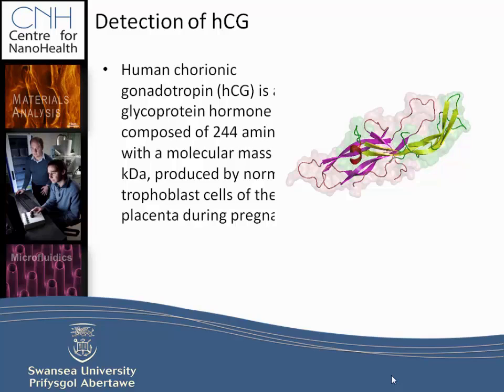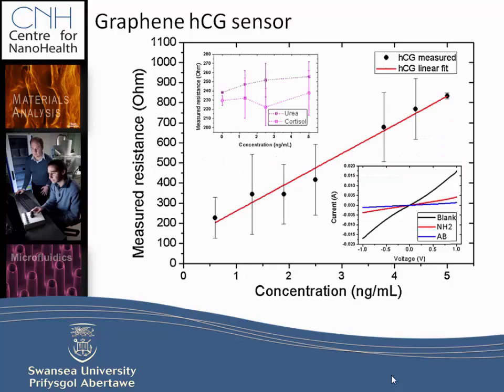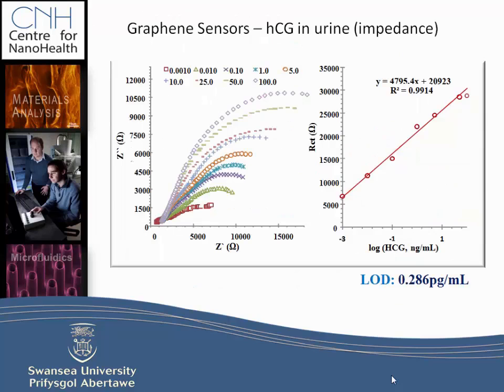We've also done quite a lot of work on HCG, and this is the pregnancy hormone. And using a different sensor platform, different functionalization chemistries, we're able to detect nanograms per milliliter using a current voltage type measurement, and then down to picograms per milliliter using an impedance-based measurement.